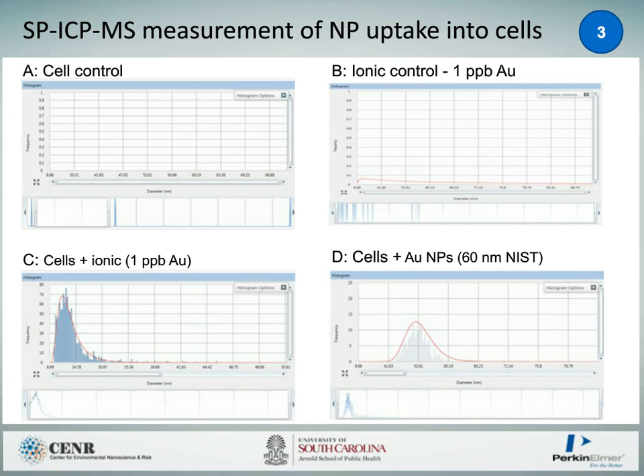So I just want to show you some results, what you'd expect to see from the single particle ICP-MS in this. So this was a 3-hour exposure, and obviously we did a cell control and an ionic control. In both of these, after 3 hours, we didn't see any nanoparticles, as you'd expect. However, if we look at C, where we had cell plus 1 ppb of gold ionic, we actually ended up seeing that we're getting some cells coming through with a certain amount of ionic within them. So you're seeing that there's an uptake from some cells.